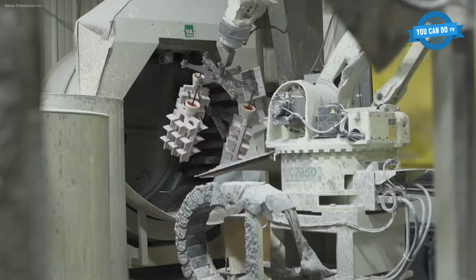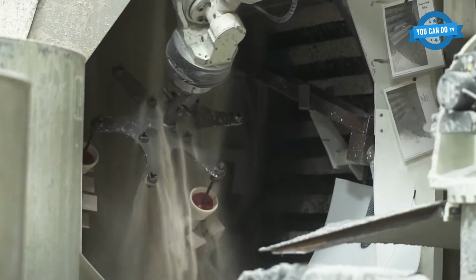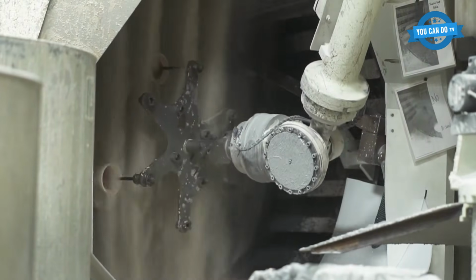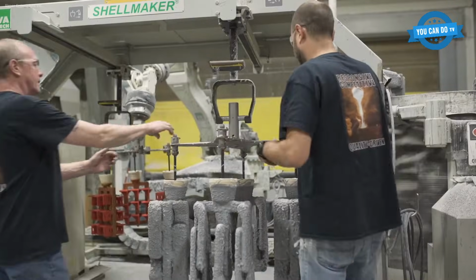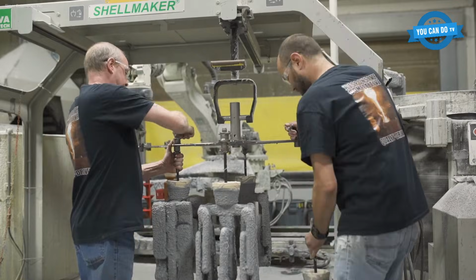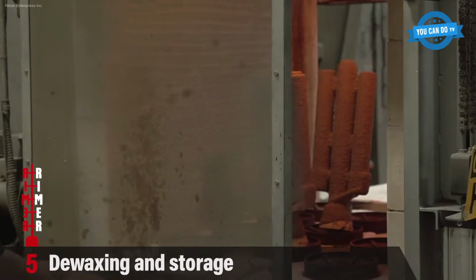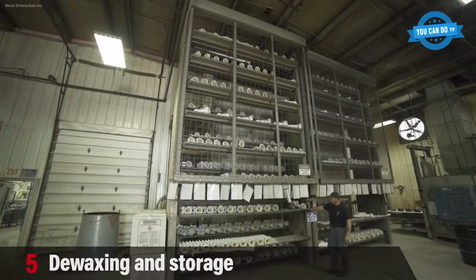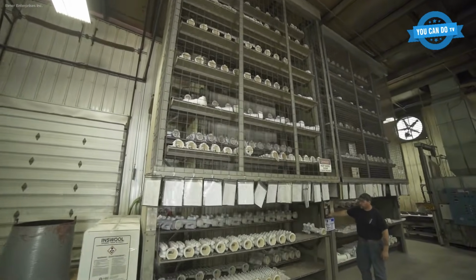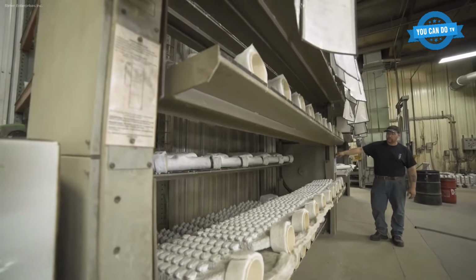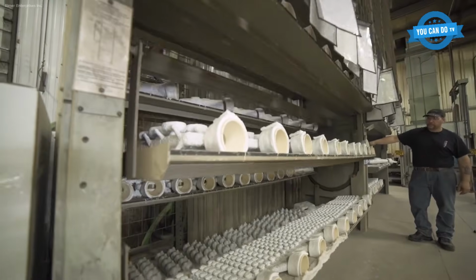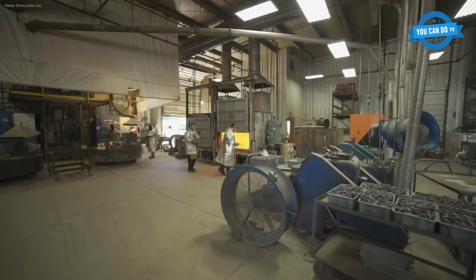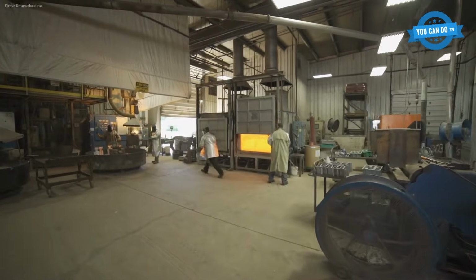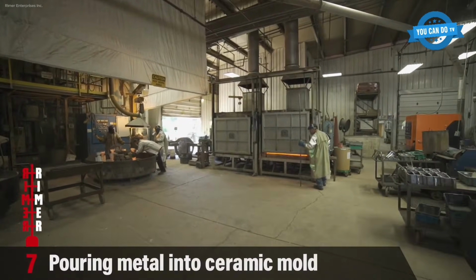Prior to casting, alloys are analyzed using the Bruker Q2 metal spectrometer to confirm exact chemical composition. Molten metal is then poured into the ceramic molds under closely monitored temperature conditions. After solidification, the ceramic shell is knocked out using pneumatic hammers, and castings are separated from the trees. Final operations include cleaning, grinding, inspection, and CNC machining, such as milling, turning, and tapping, to complete the finished component.